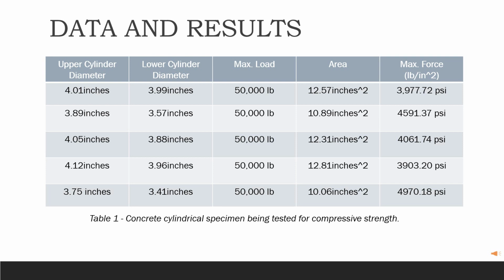concrete cylindrical specimen was the upper cylinder diameter measured 3.75 inches, and the lower cylinder diameter measured 3.41 inches. And the max load is 50,000 pounds, and the area is 10.06 inches squared, and the PSI is 4,970.18 psi.